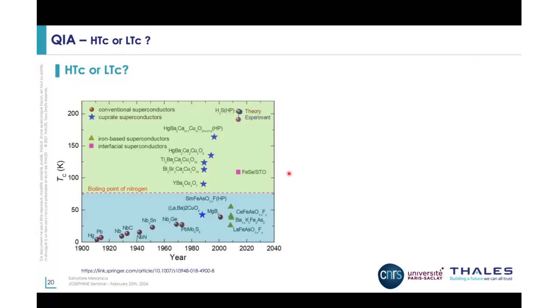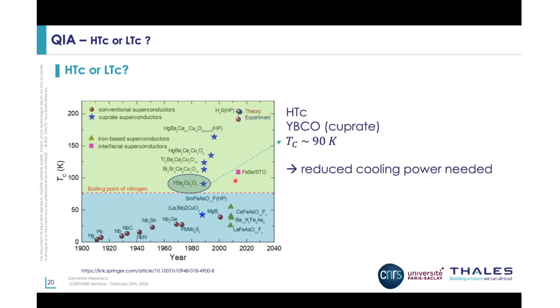But of course, it comes with a drawback. It's made of superconductors. There's no way around it. We have to cool them down. But if you go back to the table that I showed at the beginning with the exponential, well, it's even higher than an exponential because it's almost a vertical race to get to the higher temperatures. We can get away with this drawback of cooling down because we can use YBCO, and that's the material that we chose to work with, because its TC is around 90 Kelvin.